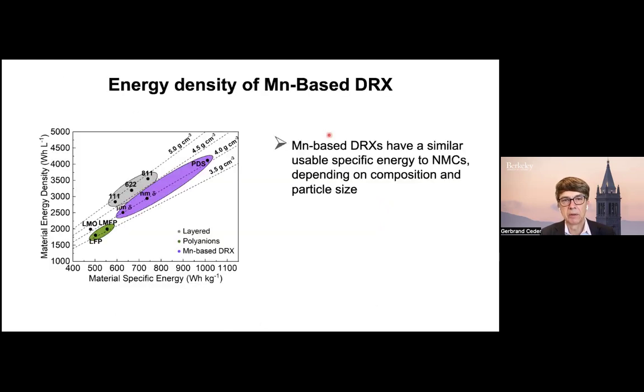So where do these materials sit, in contrast to the larger cathode landscape? I've plotted here the specific energy at the cathode level and the energy density, to compare to other materials. These are the NMCs here, and these are the LFP. LMFP is still kind of a research product. We don't totally know where it's going to end up, but probably somewhere in this green circle. What you see is that the micron size DRX, which is this one, and the nanometer size DRX, sit in specific energy at the low level of the early NMCs. Partially disordered spinel, which is the heavily milled material I showed you earlier, sits way up here.